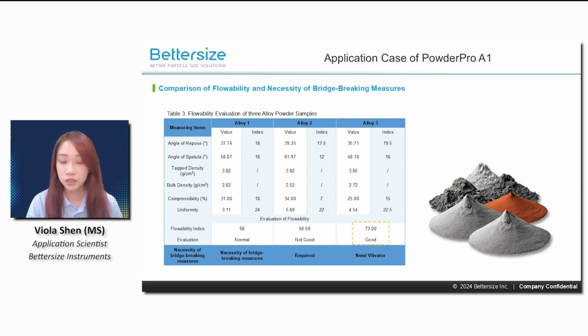In selective laser sintering (SLS), consistent powder flow is essential for uniform layer deposition and defect prevention in printed parts. So this application case demonstrates how the Powder Pro A1 was used to evaluate various parameters, including the angle of repose, angle of spatula, tap density, bulk density, compressibility, and uniformity. Each test value from the Powder Pro A1 corresponds to an index based on the Carr index method within the software, allowing for a direct flowability evaluation.